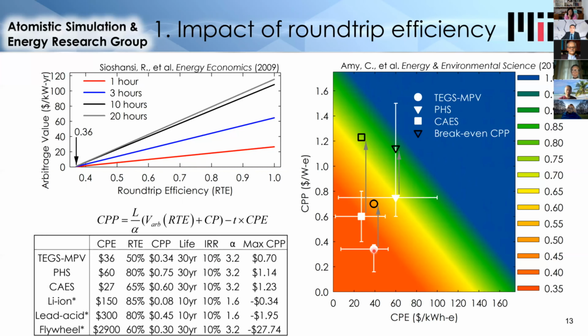So TEGS can be profitable because it's around 50% efficient, but it only needs to be 35%. On the other hand, if we look at pumped hydro, this triangle shows that the efficiency of pumped hydro would be required to be 65%. And in fact, it is 80%. So this technology is also profitable, which is why it exists.